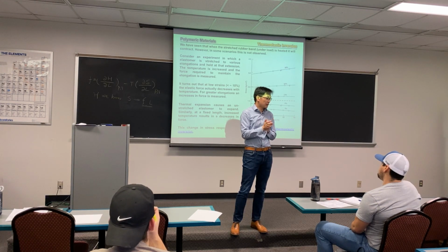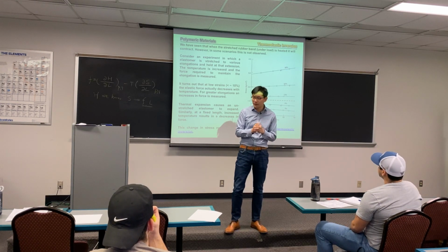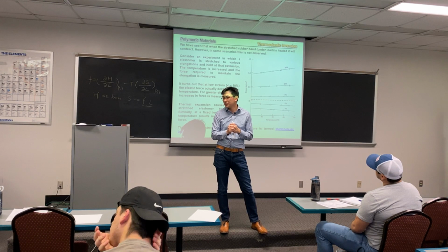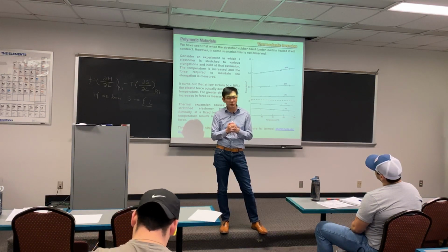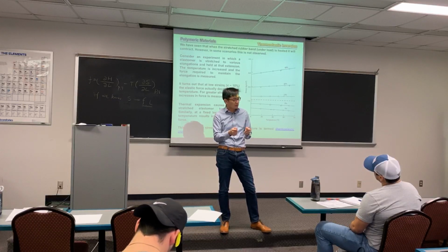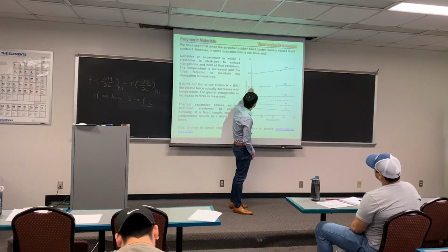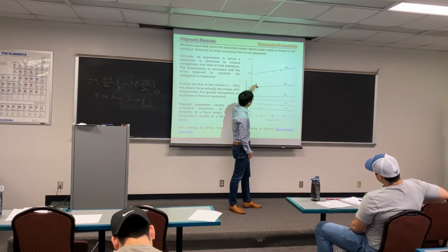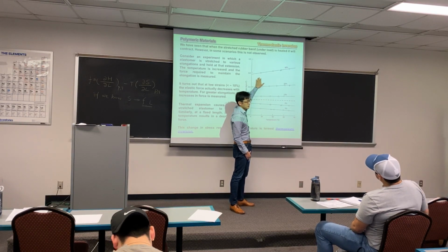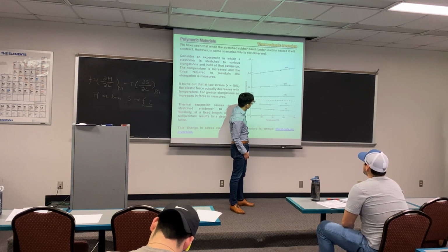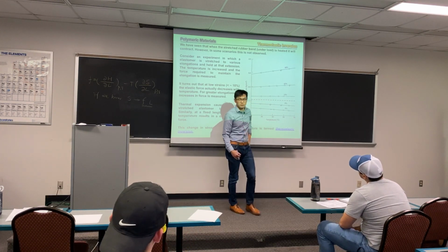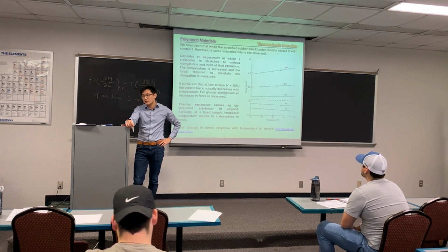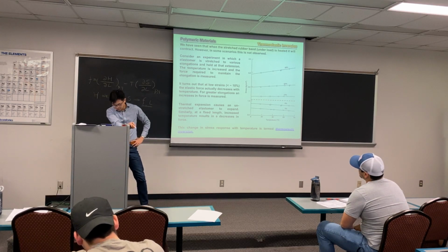That is due to the change in the modulus of your elastomer. Your modulus goes up. Your rubber gets stiffer the higher the temperature. That's why you typically expect an increase in the stress with increasing temperature. As you can see, at 13, 20, and 38 percent strain it is more obvious. But what scientists also found is that at a low degree of strain, this was not so obvious. This concept is called thermoelastic inversion, and this is purely due to thermal expansion. Okay?